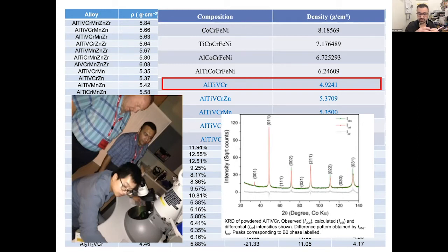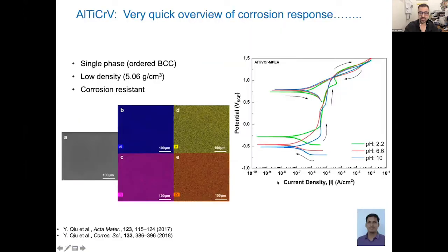So there's some ordering. It turns out that the body-centered atom in these alloys was always aluminium, and for the corner positions, titanium and chromium would always be in a heavy fight for the corner positions. That doesn't matter so much here. But what's interesting about this alloy, and now we move to some work that a current PhD student, Xuejie, has been doing, is that it's extremely, extremely corrosion resistant.